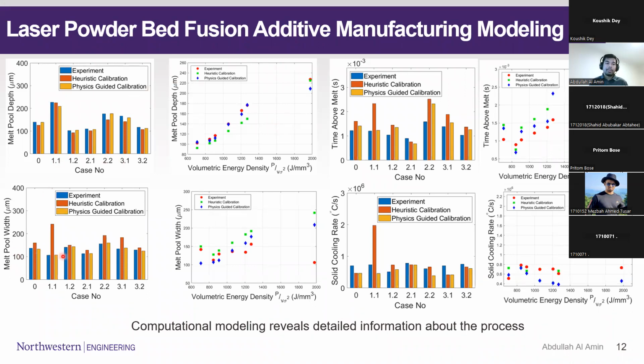And also this is the melt pool width, meaning how wide the melted region is. Again, I tried to compare them with two different alternative techniques that I have implemented, and I also plotted them against the volumetric energy density. As you can see, the red one does have some discrepancy at higher volumetric energy density, meaning there are higher errors. But if I improve my heat source approximation technique, it also improves the prediction capability.